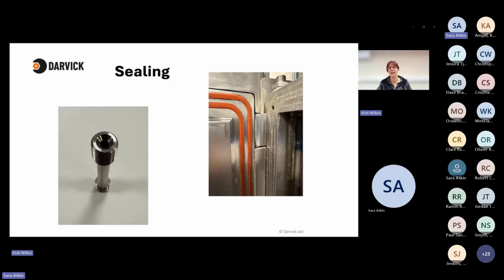The other technique is double sealing. So basically in a chamber like you've got on the right hand side, you can see the double seals, and we will have an inert gas that runs in between those seals. So again, if the hydrogen gets out of the sample into the chamber, that inert gas will ensure that it stays in the chamber until it's extracted through the proper and safe system.